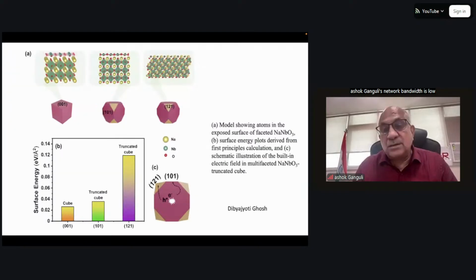So this can be shown during these calculations. You can also do surface charge calculations, and you can show what kind of surface charges are there on these different facets. And these calculations also explain why certain shaped particles have more efficiency by calculating the surface charge. So you can see the surface energy is highest for the (121) planes of the truncated cube. Okay, so you can calculate the different planes and what is the surface charge and surface energy.